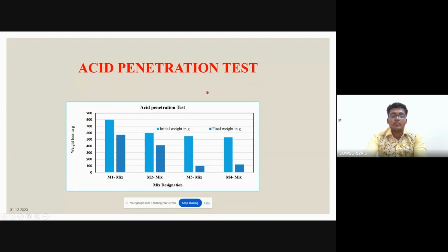In the acid penetration test, we drop the panels in hydrochloric acid, and by checking the initial weight and final weight, we identify the weight loss. In mix 1, the initial weight is 800 and the final weight is 550. In mix 2, the initial weight is 600, and after dropping into the HCl, the final weight is 400. In mix 3, the initial weight is 550. After dropping into the HCl, the final weight is 100. And in mix 4, the initial weight is 550, and the final weight is 120.